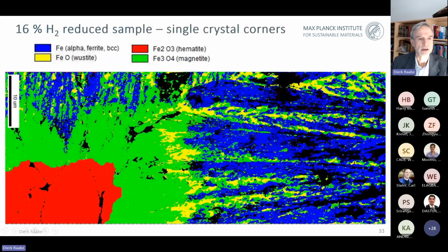You get a sense of the misfit between these two phases, but otherwise they seem to be pretty coherent in part. When you go deeper into single crystal work, something that we are currently doing, that's some unpublished work, you see how very, very complicated that can become. Because even though you start with very clean conditions and very clean single nucleation, you have, like you see here on the left-hand side, the hematite, on which the magnetite is then formed, as you can see here.